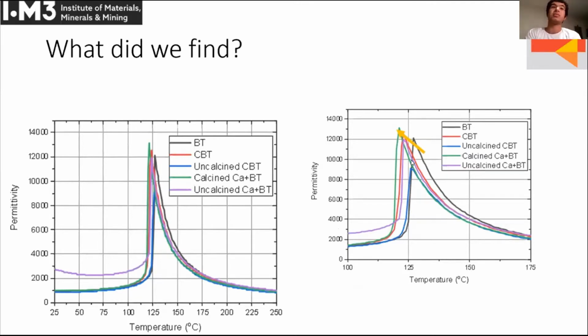And as we add calcium, we start moving to the left. I'll try and point your attention towards the red and the green, which are the ones with the calcination steps. We can see that these have moved further to the left and have higher peaks. So essentially, this proves how important the calcination step is — it gives rise to more pronounced effects, so a larger decrease in the Curie temperature and a larger increase in permittivity as well.